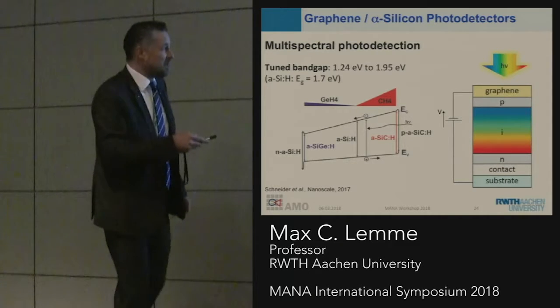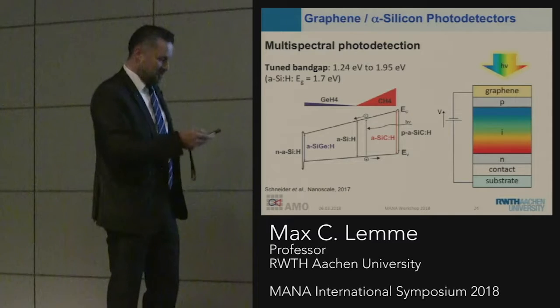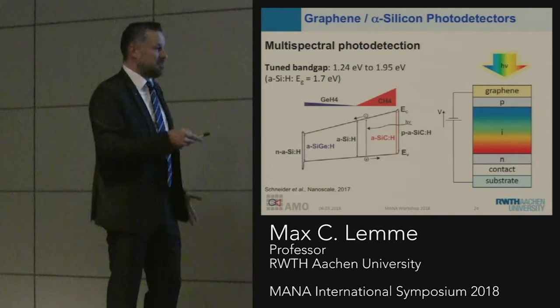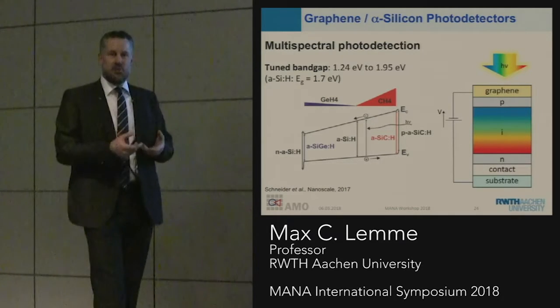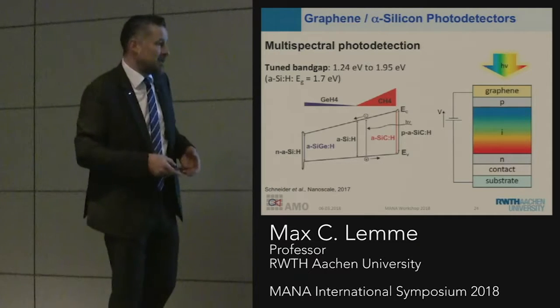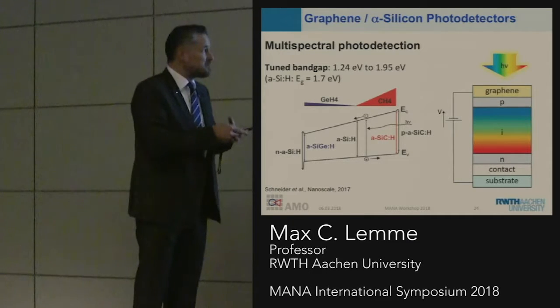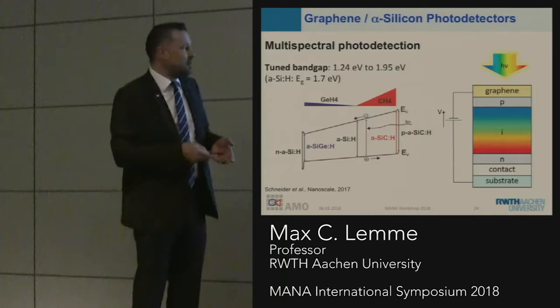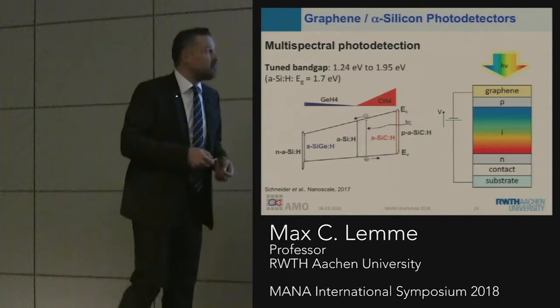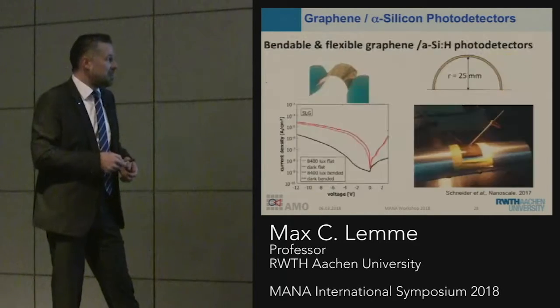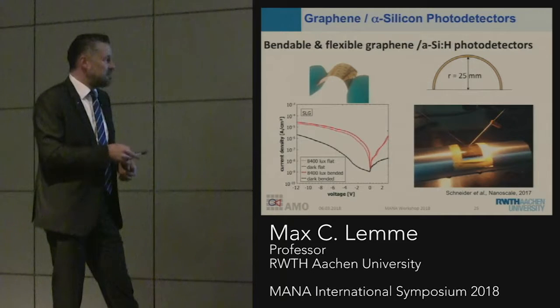And the graphene here is really only a transparent conductor. But what it does is add flexibility, because the amorphous silicon is somewhat flexible. The graphene is very flexible, but conventional transparent conductors are usually very brittle. So now we can make these multispectral photodetectors, and we can make them on flexible substrates. You can see this is bended here.